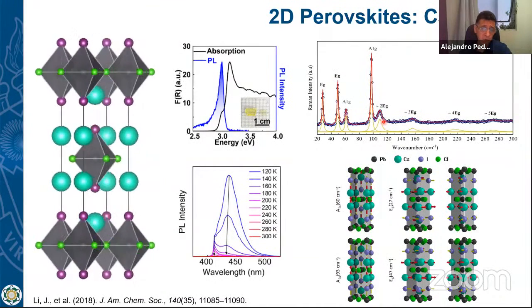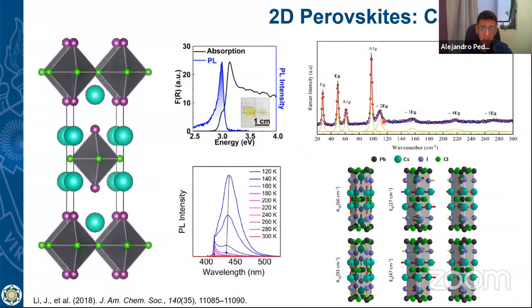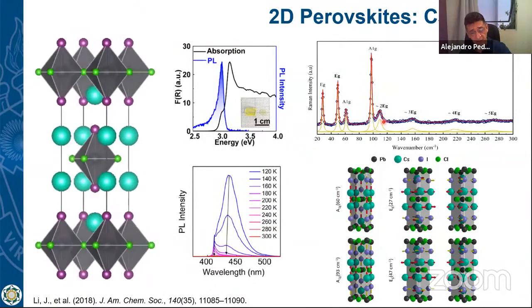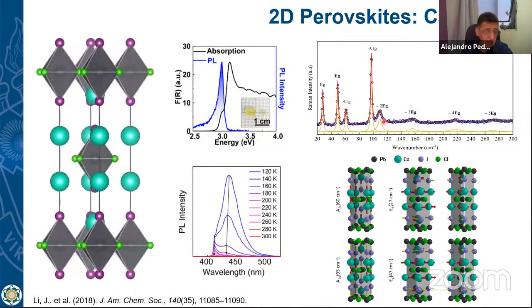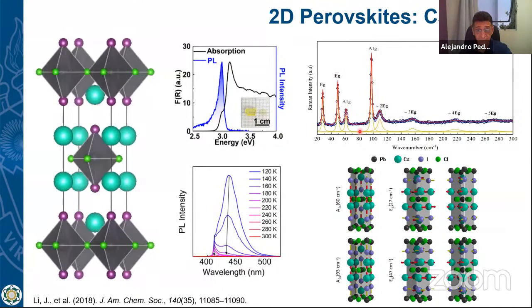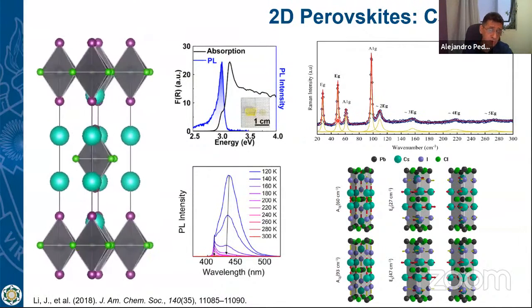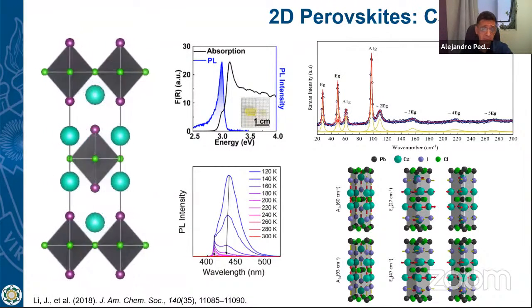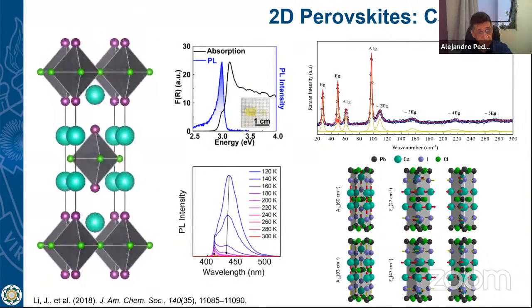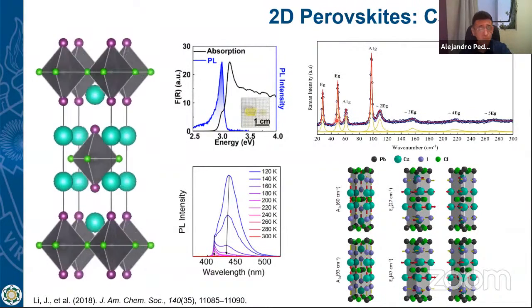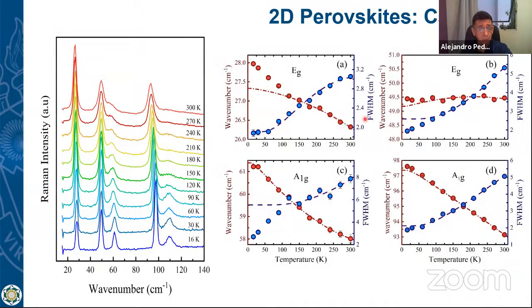There are some vibrational modes which can be observed in the Raman spectra, some of them can be observed in the infrared, some of them in both, and those things are determined by the symmetry of the crystal. In this case, the modes observed in Raman are not allowed to be observed in the infrared and vice versa. But the anharmonicity could break this rule. If we measure as a function of low temperature, you can see that anharmonicity is growing at low temperature. And there are some strange things happening around 100 Kelvin, but no phase transition can be observed.